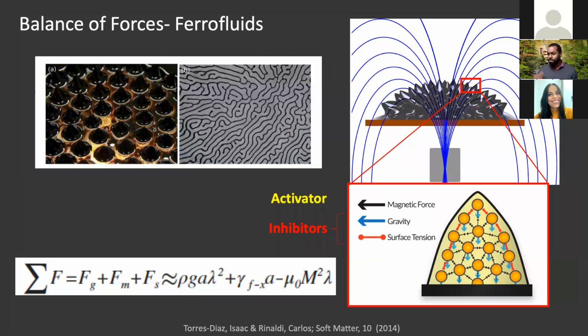So this essentially is a balance of two forces. And one system that we can use to easily cycle through these different phases is a magnetically responsive liquid called a ferrofluid. Ferrofluids, if you've seen them before, most times you see in this spike formation. And the spikes will form parallel to the magnetic field, to the magnet. You have the magnet down here, ferrofluid above, and as you get it closer to the ferrofluid, you start to see these spikes grow.